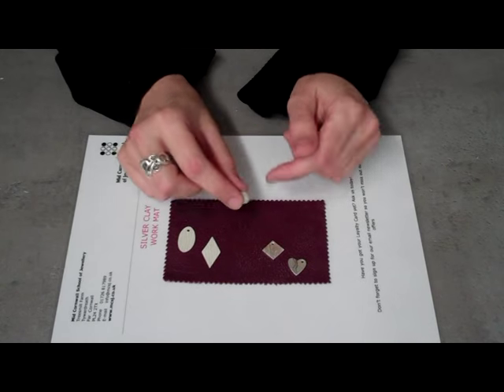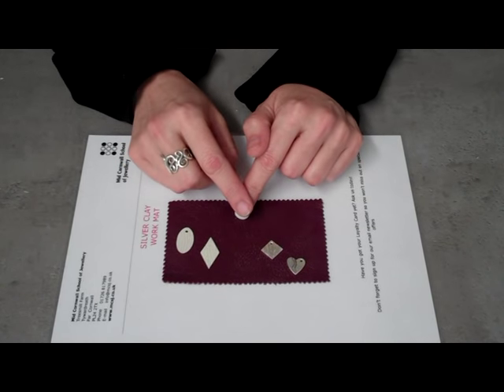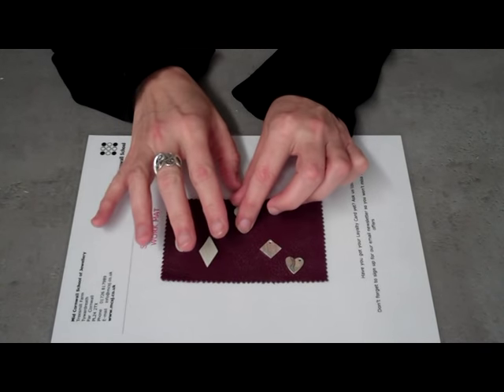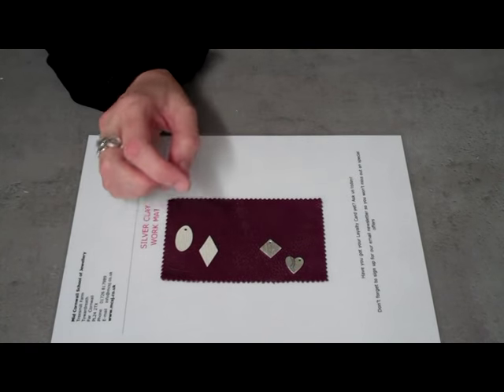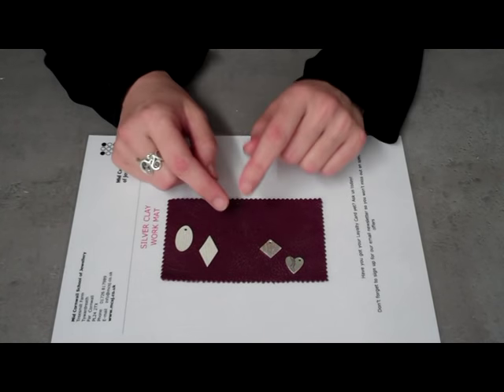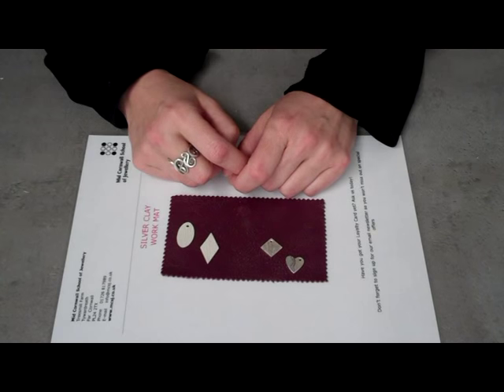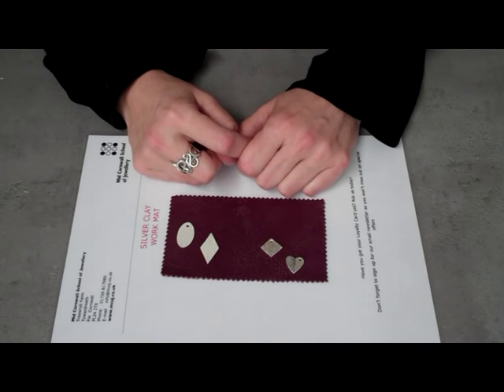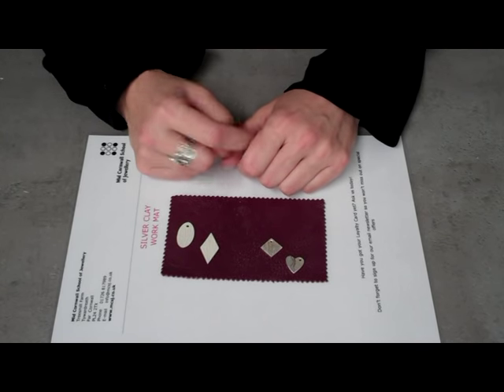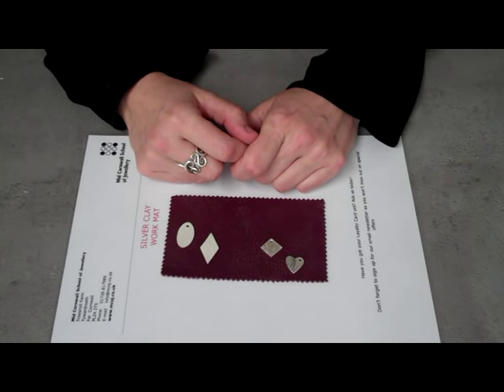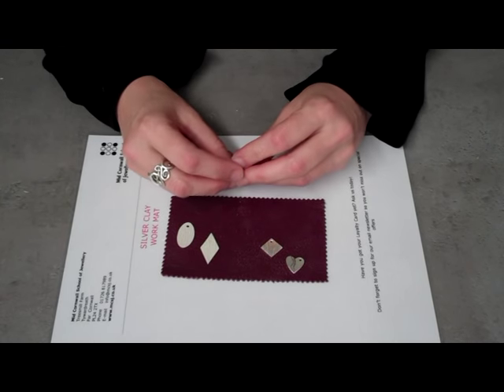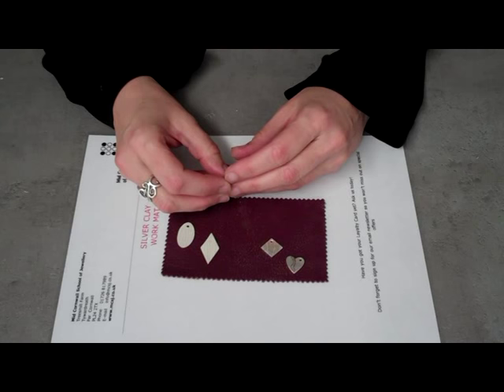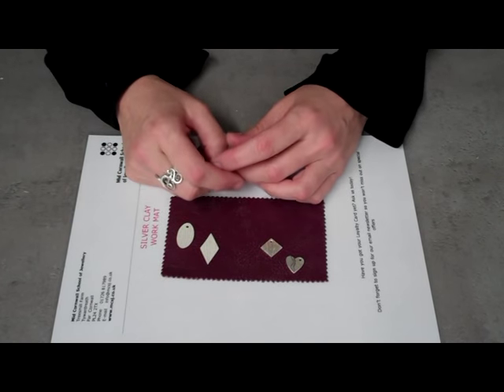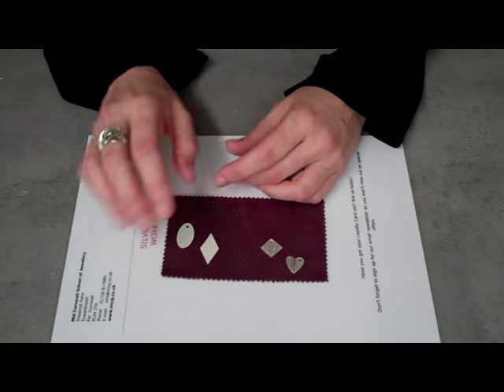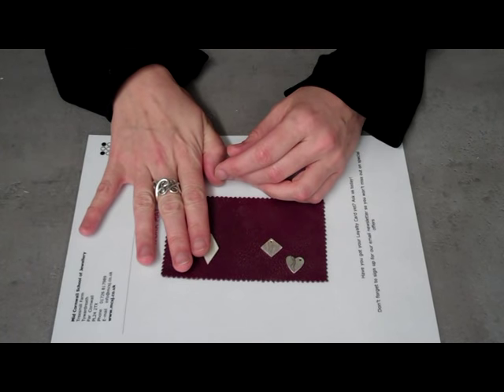But then we need to put the clay aside when we've made our shapes and textured it and let it dry out, okay? And this is very important because if there's any moisture left in the clay, when we come to fire it in the kiln or with the torch, the moisture that's left inside the clay will turn to steam and make a distortion and possibly burst the surface of your clay. So it needs to be thoroughly dried out before we can go on to the firing stage.